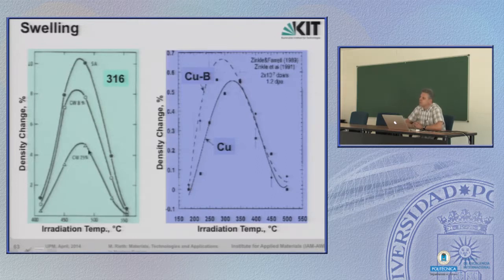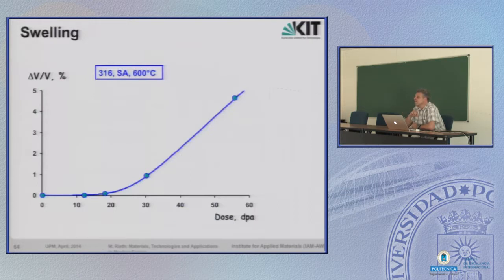And if you remember right, dislocations are sinks where vacancies try to move. And so if you have a lot of dislocations there, then many vacancies also try to locate themselves along the dislocation. But interstitials do the same. So all these many dislocation lines are the natural recombination centers for vacancies and interstitials. And so if you have higher dislocation densities, then the amount of surviving voids is smaller, and then the swelling is less pronounced. The same is true for copper. In copper, the peak swelling occurs around 300 to 350 C. So in principle, for all metals, swelling behavior is the same, which is wrong, because I forgot to tell you, and this we see in a minute, that this also depends on the lattice structure.